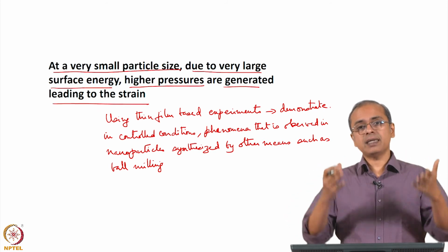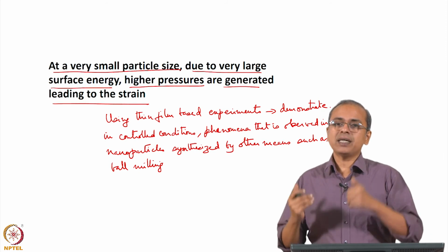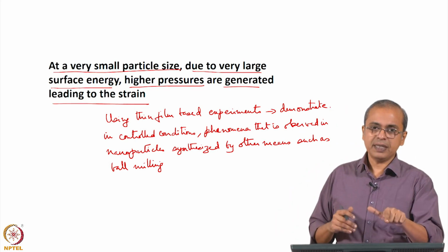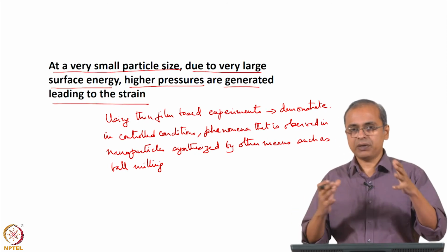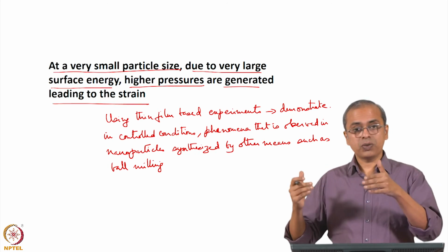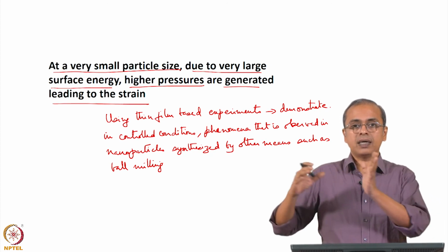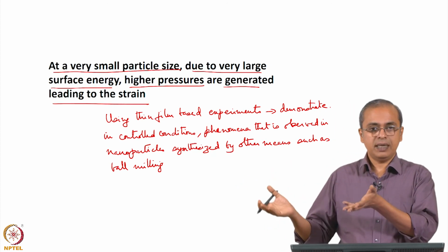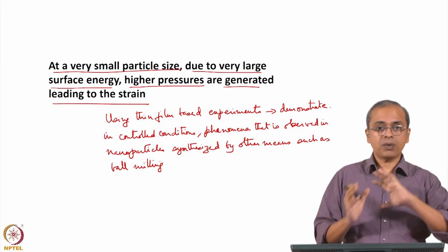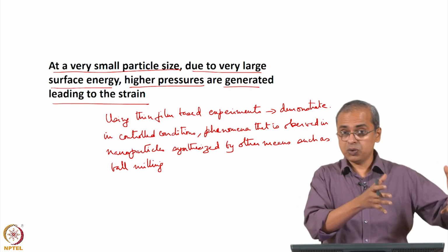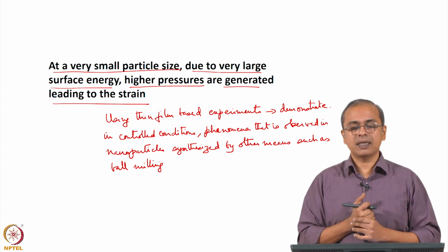So, you have a much greater possibility that you are getting a much purer product, and therefore with greater confidence you can say that the property I am seeing is that property of that particular oxide layer rather than something else. So, you get that kind of control, but it is not a particle. So, you are then trying to extrapolate some result from that thin film to another synthesis process, which is the ball milling kind of process, and then trying to understand why there is a phenomenon that is showing up in both cases. You have understood that there is some, let us say, stress in this case, could be something else in another experiment you are doing.